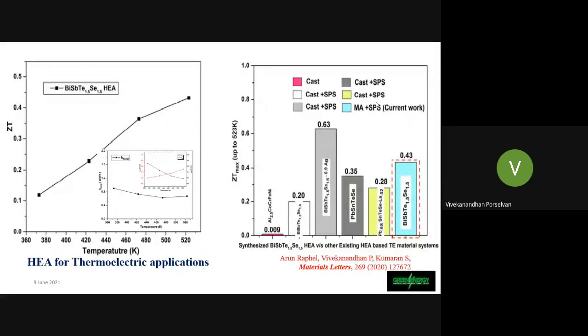So here is another alloy, the high entropy alloy that is made with bismuth, Sb, Te, Se. Here also we can see that there is a drastic reduction in the thermal conductivity, and we are tuning this particular structured high entropy alloy as a semiconducting material.